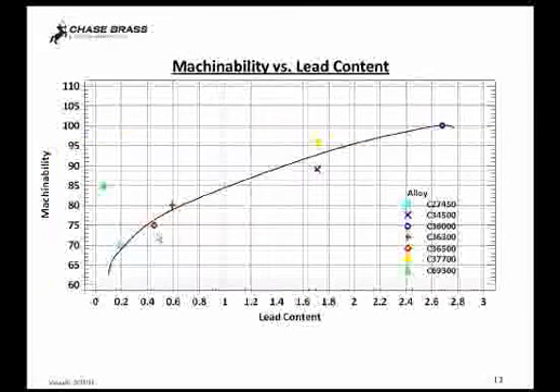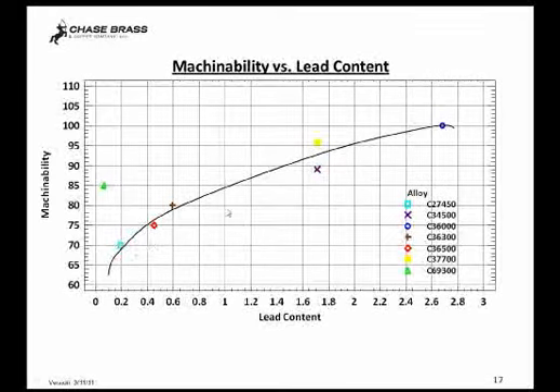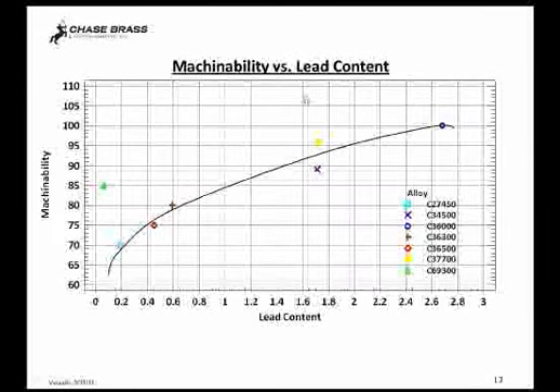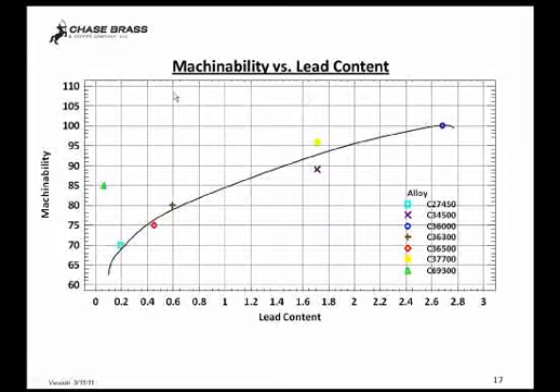If you're relying on lead for machinability, then there's a relationship as shown by the curve here. As the lead content goes up, the machinability, vertical axis, you can see goes up. Or conversely, as the lead content comes down, the machinability comes down. And legislation that we've been talking about has been driving the lead content to lower and lower levels, so that in order to get maximum machinability for people who are machining these water components, other avenues have to be pursued.